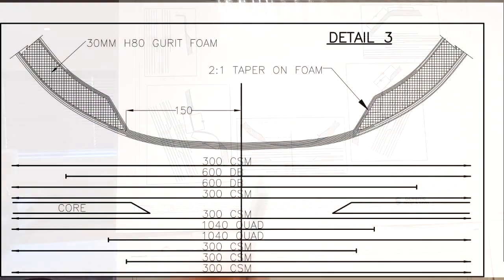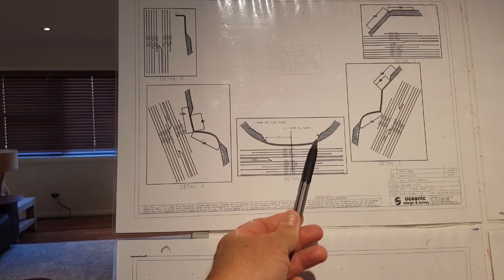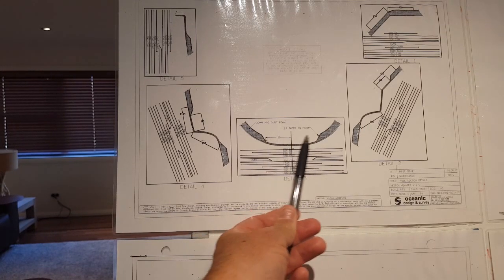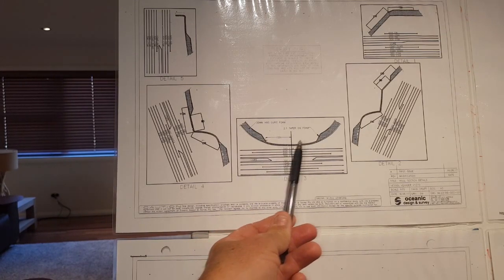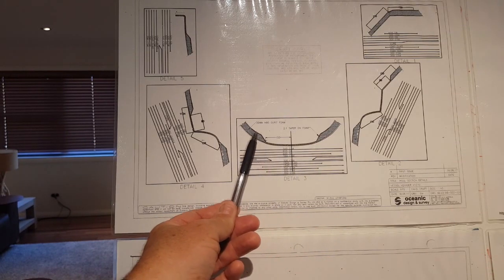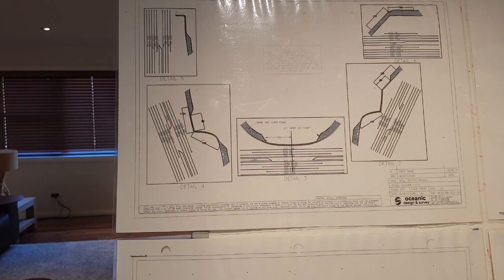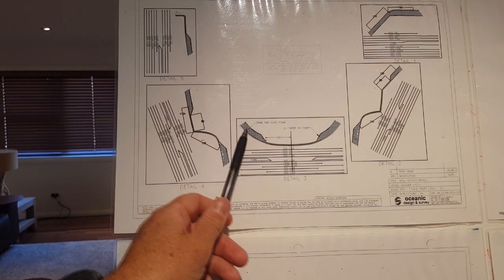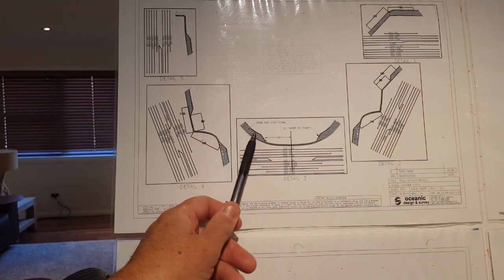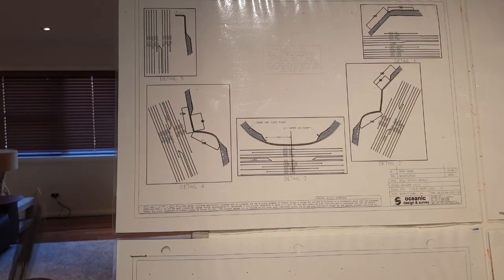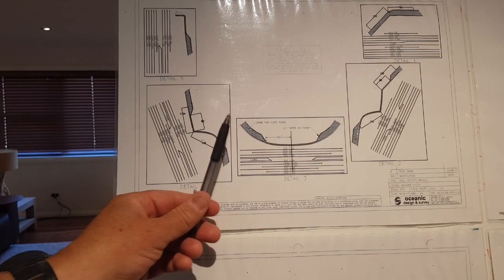Obviously this part here is in the bottom of the hull. So we have solid glass along the keel line for 30 centimetres, or 150 mil either side of the centre line, and then we have 30 mil H80 Gurit or Divinycell foam. Now this foam here wasn't in the original plan. The original plan was solid glass, and this boat actually weighed in around about 8 tonnes dry weight. That's before putting fuel and water, etc.